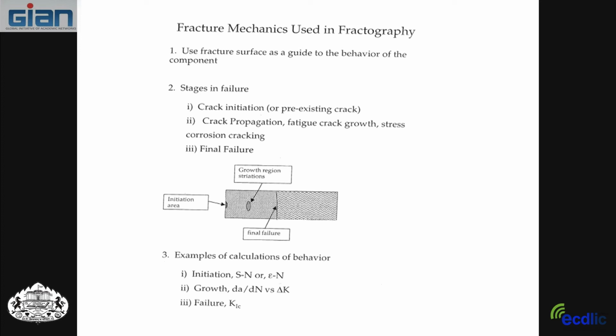You might see a fast fracture area. In fatigue, in some materials, you can look under a microscope and see what's called striations. I don't know if any of you ever encountered that. They're little ridges, and each ridge is one fatigue cycle. And they're fairly small. So if the fatigue crack growth rate is 1 × 10⁻⁶, you would see that size of ridges, that distance between ridges.